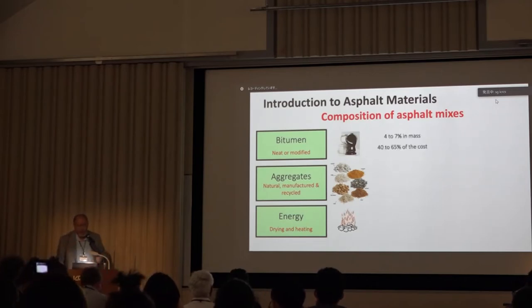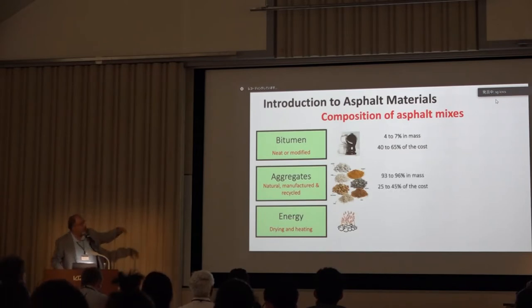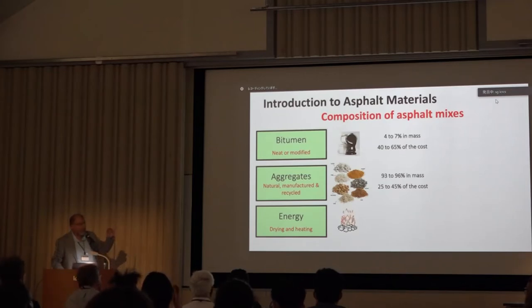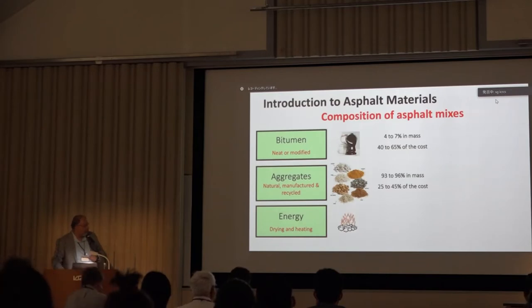And we know that the materials have different behaviors. So typically we have 4 to 7% binder in it. It represents most of the cost, and it's the most important part of the mix. The aggregates are very, very important. They represent almost roughly 95%, and the energy represents 10 to 15% of the cost of the mix.